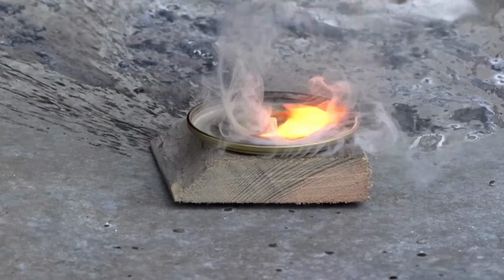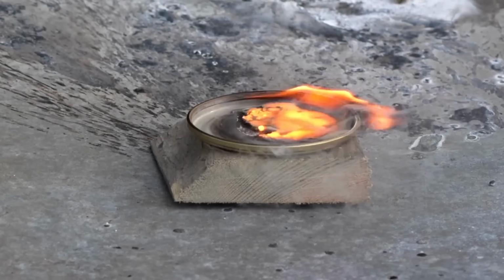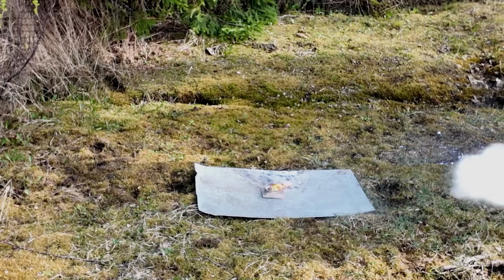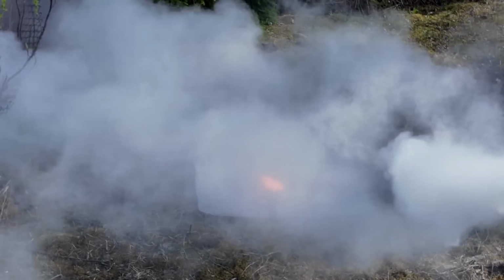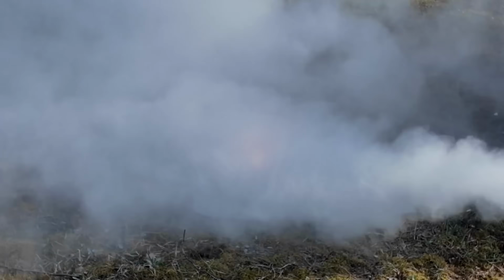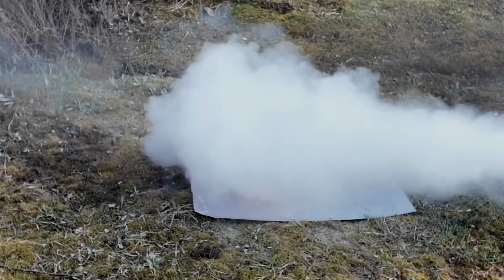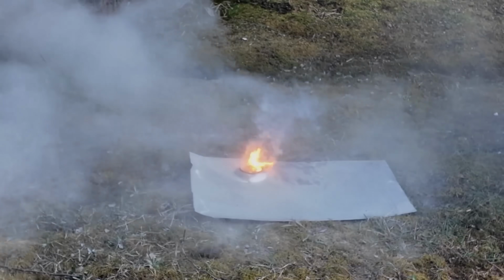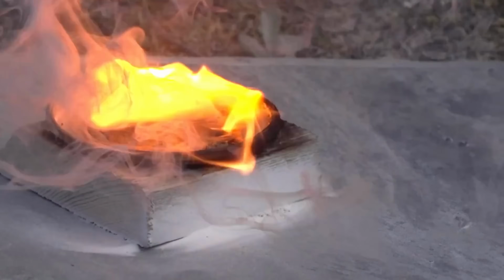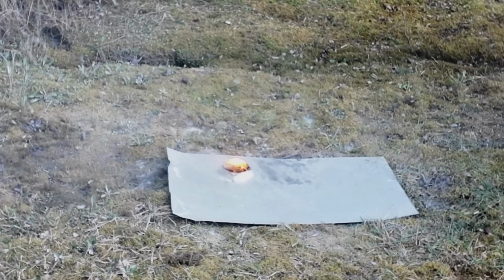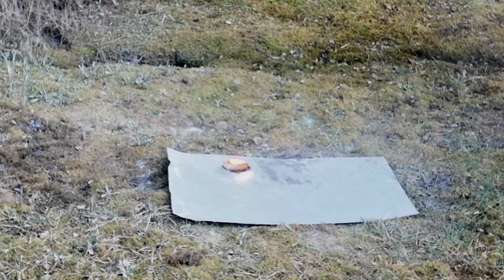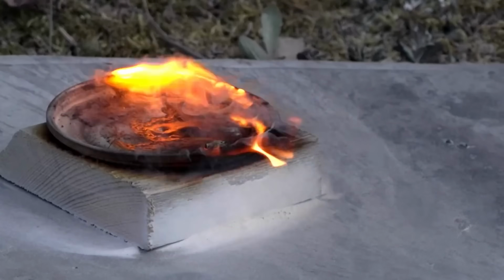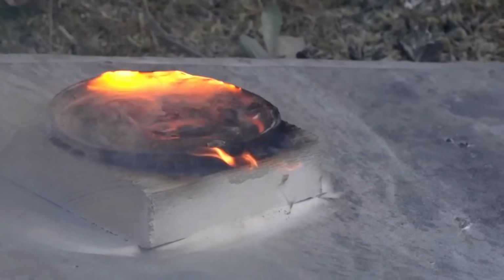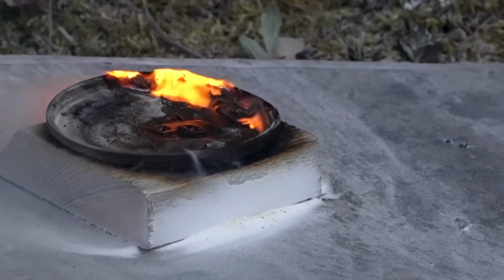The first metal I set on fire is sodium. Then, I try to put it out with a dry powder fire extinguisher. Surprisingly, even this type of extinguisher does not cope with burning sodium, and the fire remains as strong as it was before. Apparently, molten sodium, which is a good reducing agent, reacts with ammonium salts and most likely recovers sulfur and phosphorus from ammonium sulfate and phosphate. The distinctive odor of hydrogen sulfide left after extinguishing proves this point, by the way.